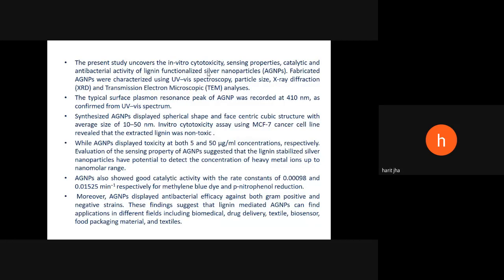This again deviates. So, if there is a change in the color, if there is a change in overall pattern or spectroscopic property of the specific nanoparticle taking place at a given concentration of metal ion, it means the metal ion is interacting with the nanoparticle and causing that particular change. So the sensitivity or the affinity of the lignin functionalized nanoparticle for that particular metal ion is quite high. So in that case, we can use this nanoparticle solution as a sensor for detecting the presence or absence of toxic metal ion.